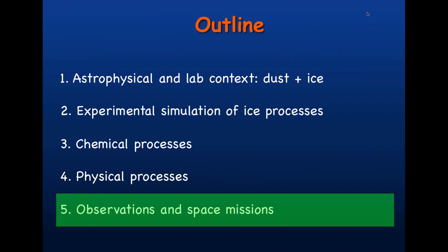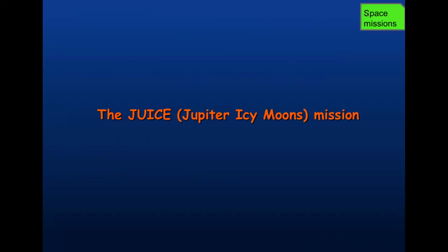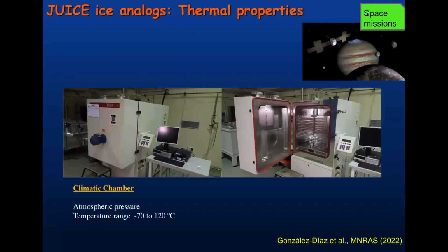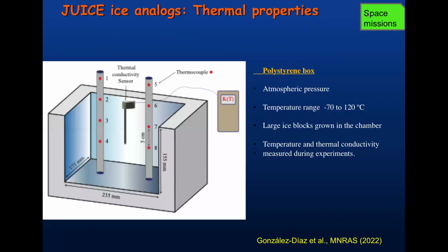And finally, I will talk about the application to observations and space missions of our work. So for the JUICE mission, the Jupiter Icy Moons mission, we did some experiments using the climatic chambers at INTA to reproduce cold temperatures and warm up the ice. And we used a bucket. So we are not talking anymore about microscopic ice. This is a regular box where we grow the ice and we monitor the temperature. We measure the thermal conductivity of the ice. And furthermore, this ice is a solution with salts, like you have in Europa and other icy moons.